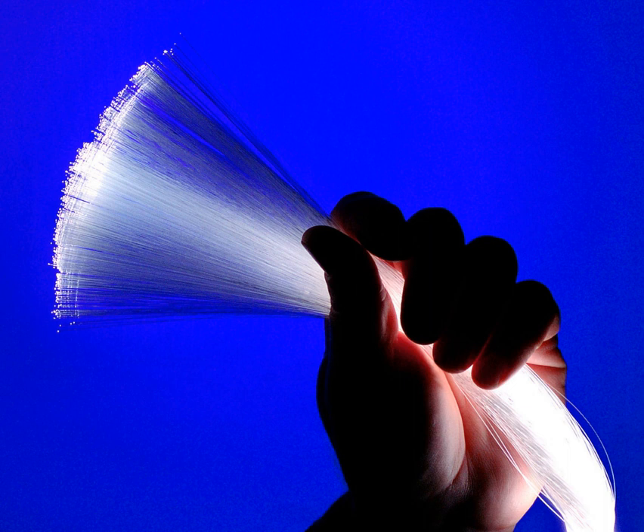Typical communications fiber uses a circular preform. For some applications such as double clad fibers another form is preferred. In fiber lasers based on double clad fiber, an asymmetric shape improves the filling factor for laser pumping. Because of the surface tension, the shape is smooth during the drawing process, and the shape of the resulting fiber does not reproduce the sharp edges of the preform. Nevertheless, careful polishing of the preform is important, since any defects of the preform surface affect the optical and mechanical properties of the resulting fiber. In particular, the preform for the test fiber shown in the figure was not polished well, and cracks are seen with the confocal optical microscope.